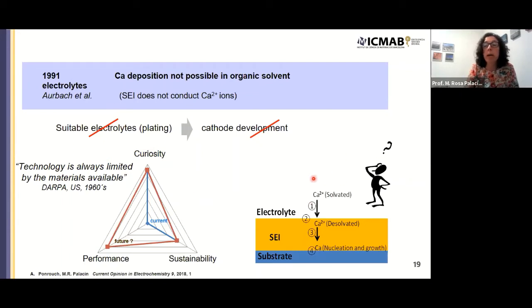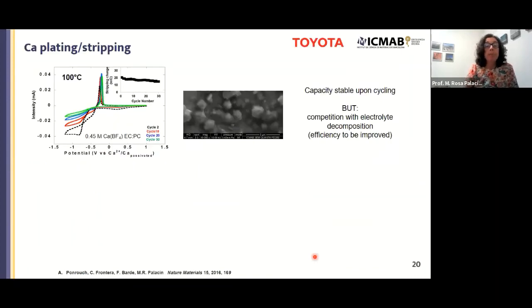Is it because the migration of solvated calcium ions in the electrolyte is a problem, or because desolvation at the surface of the negative electrode is an issue, or because, as was pointed out, the transport of calcium through the passivation layer does not take place, or finally, it is a problem to nucleate on the surface? We started to work on this topic, and we realized that the main issue was the formation of ion pairs in the electrolyte, due to the fact that calcium has a 2+ charge. This formation of ion pairs was limiting migration of calcium in the electrolyte.